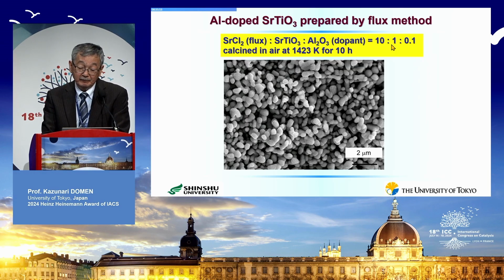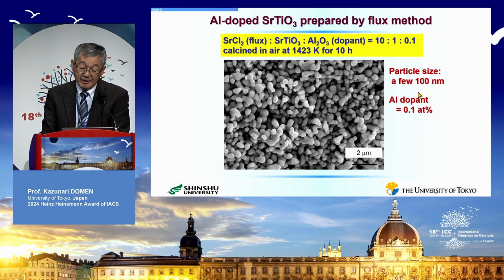The ratio is 10:1 to 0.1. Then we calcine this mixture in air at 1423 Kelvin for 10 hours. Then we can get this kind of particles. The particle size is about a few hundred nanometers, and the amount of the aluminum dopant was about 0.1 atomic percent.